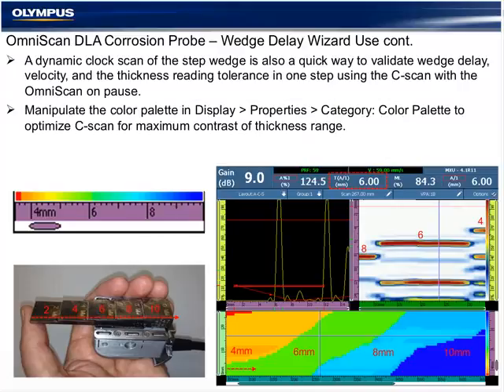In this example, I've set my gate over the area to include the lowest reading on the step wedge, which is 2 in this case, and long enough to include the thickest, which is 10. So whether you're in inches or millimeters, whatever your calibration reference standard is set for, you change the OmniScan accordingly, and we'll take a quick look at a calibration scan in OmniPC.